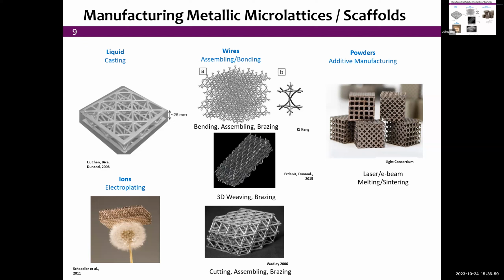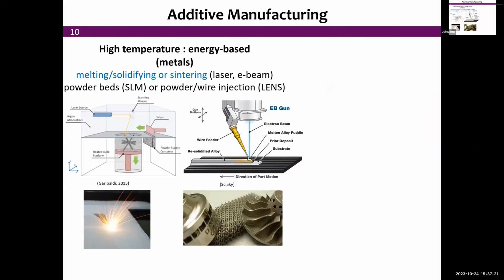or even woven into those 3D structures. And of course, from liquid to wires to powders, we can use additive manufacturing using powders, where typically people melt with laser or E-beam, and also in some cases sinter the particles, which is, of course, a slower process, but is not quite as extreme in terms of temperature cycling of the material. So this is the way it's done.